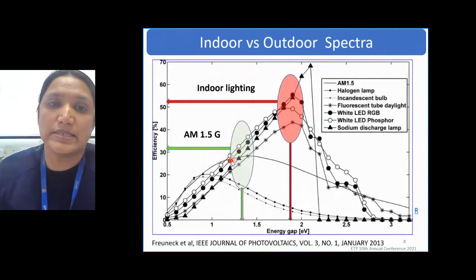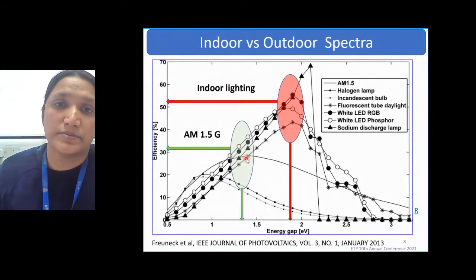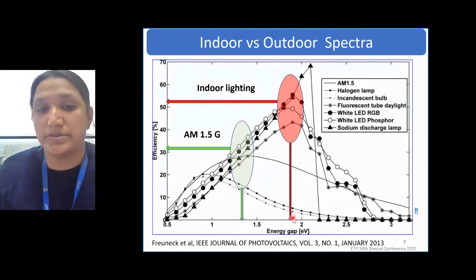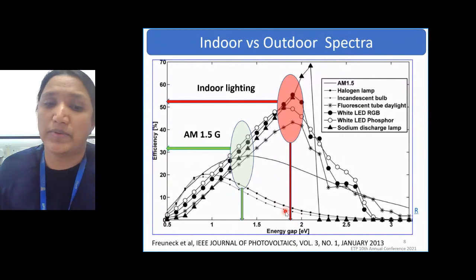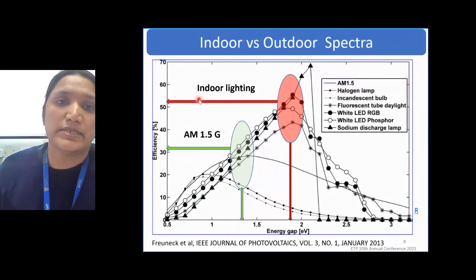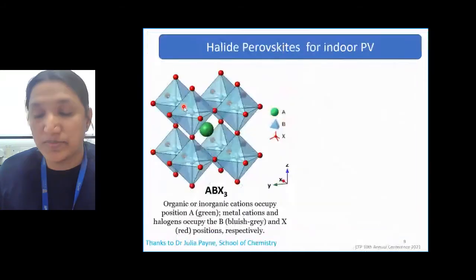So these differences in spectra bring additional requirements for band gap. Theoretically, it is calculated that for maximizing indoor light harvesting, the optimized band gap is around 2 eV, around 1.9 eV, and with optimized material and device architecture, the efficiency can reach more than 50%.